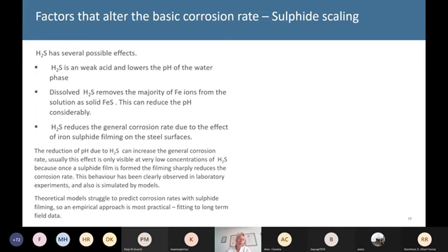But the drop in pH that we see when we add H2S, if you have just a few ppm, can actually cause a small increase in corrosion rate. But generally, once you get to tens of ppm or mole percents, then you normally see a real high drop-off of the corrosion rate. Now, it's been very difficult to get modelling of this from any kind of laboratory experiment, because all you measure in laboratories is a really low corrosion rate. It's hard to get anything really practical from it.